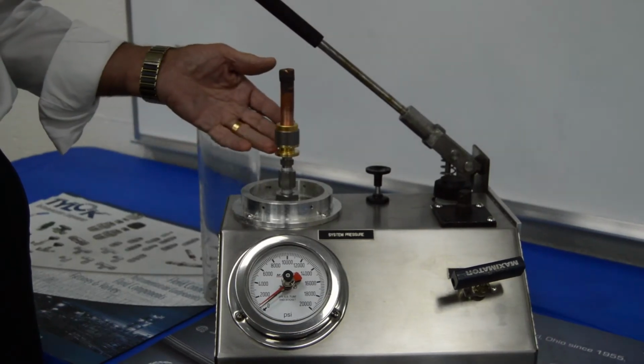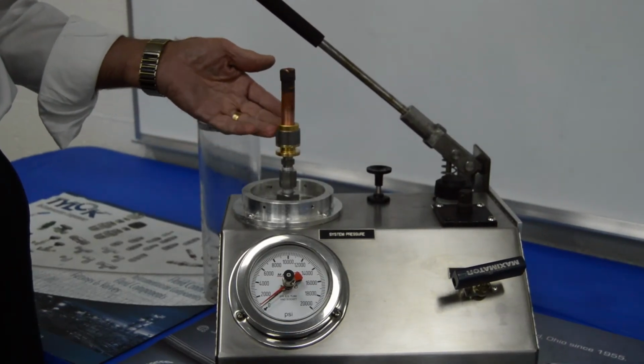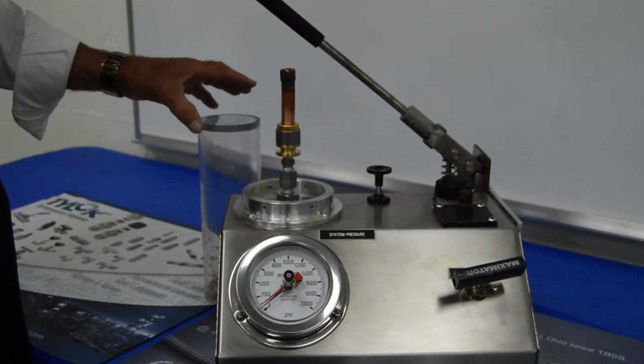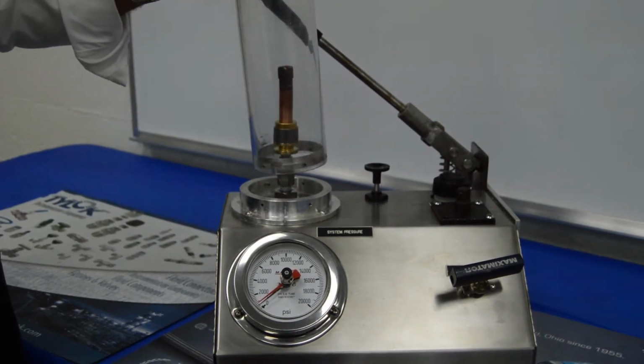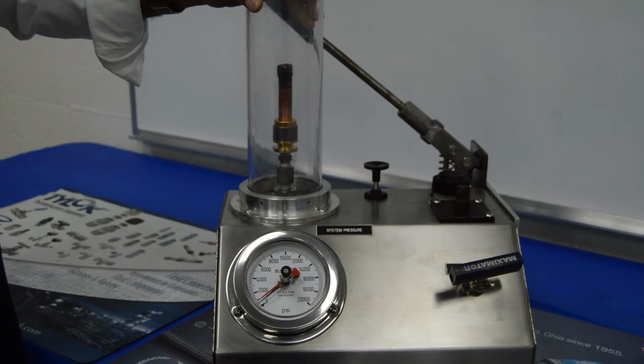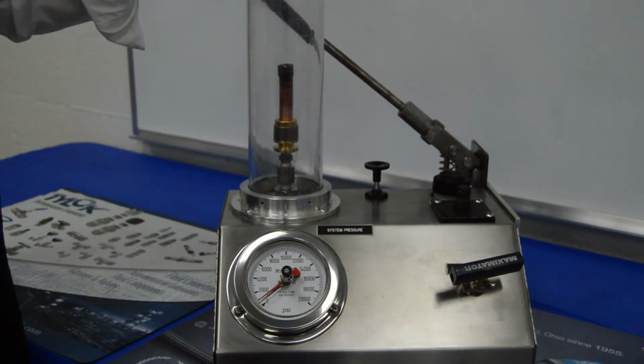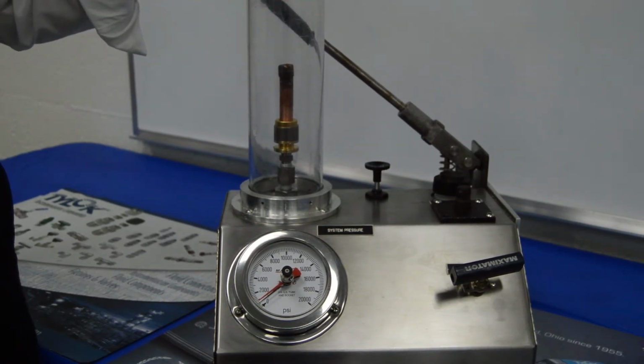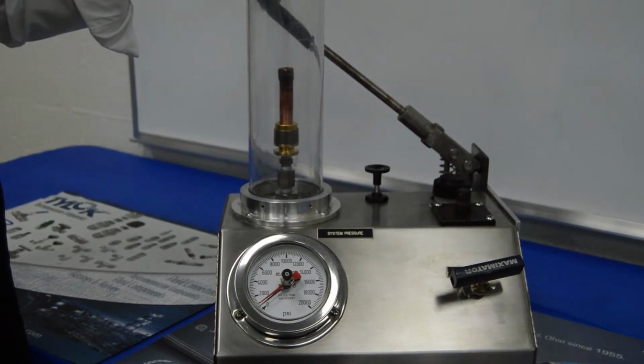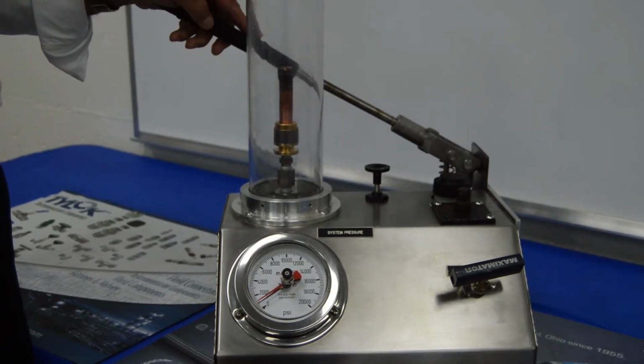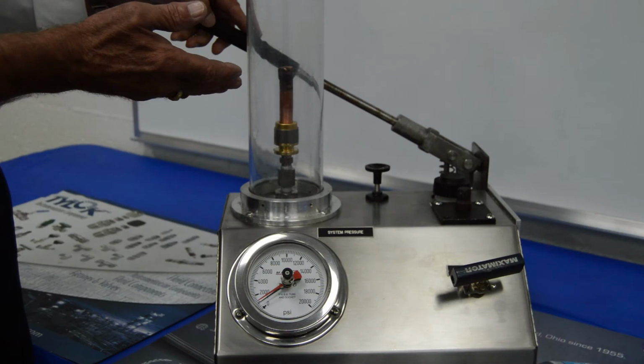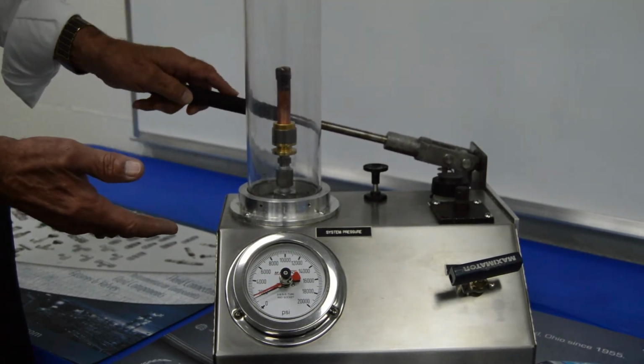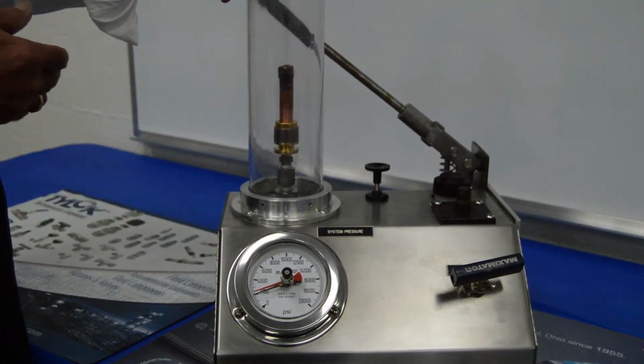I've installed the Medlok fitting with the tube into our test chamber, and we're now going to put in the safety guard and start to pressurize the fitting. This K tubing is rated at 1682 psi, but it is fully annealed from the cap that was brazed on the end. So we're going to see what kind of pressure we can get up to.